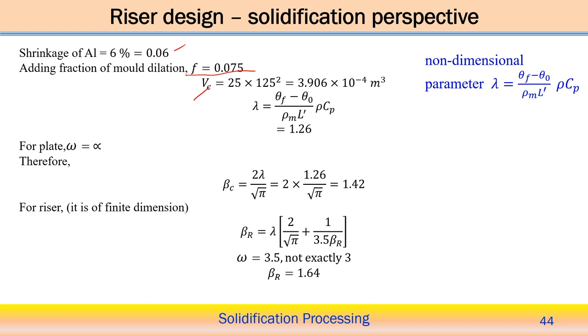Now, the cast volume we can calculate. And we know the non-dimensional parameter lambda equal to theta f minus theta 0, rho m L by rho Cp, that we can calculate. If you remember, during the casting process, when you consider the curvature effect also in the casting solidification, there we can see this kind of non-dimensional parameter: theta f minus theta 0, rho m L by rho cp. So, there we can calculate lambda equal to 1.26. This lambda can be calculated like that.